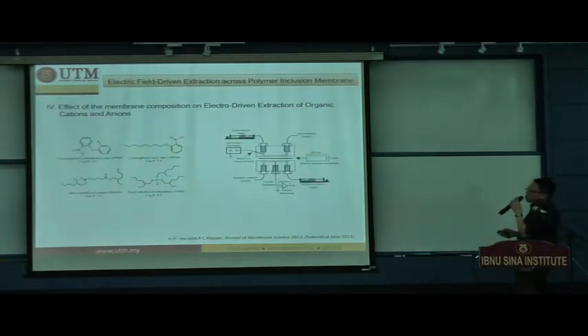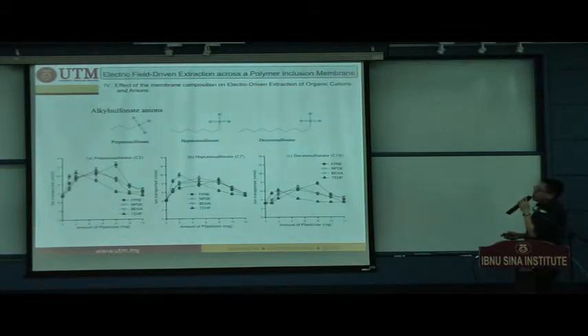So we chose 4 types of plasticizer: a very less hydrophobic one, NPOE, a medium hydrophobicity one, MPOE, BEHA with a 7.8 log P value, and also the most hydrophobic, TEHP, as our testing materials. So the setup is similar to the previous one, and you can see for the extraction of organic anions, very interestingly, for each of the plasticizers that you use, they only show optimum conditions at different amounts of plasticizer.